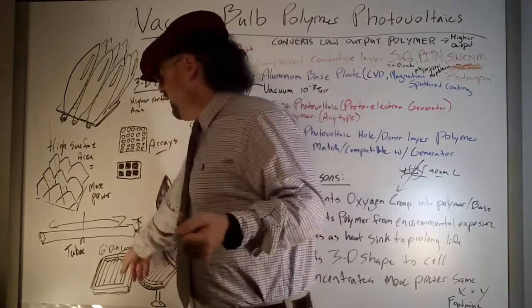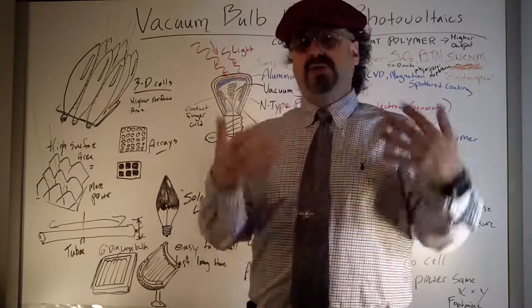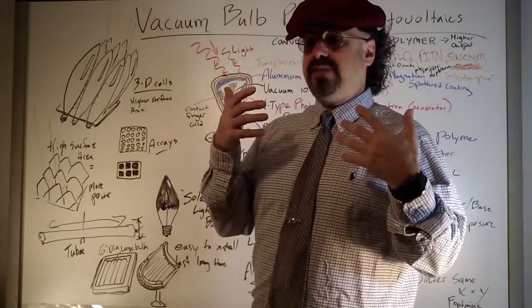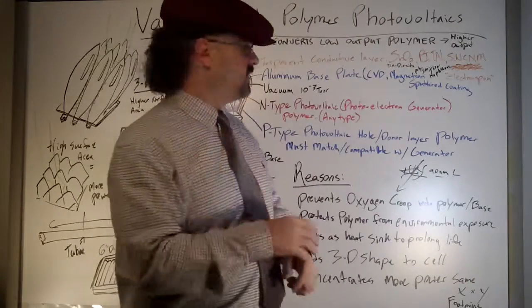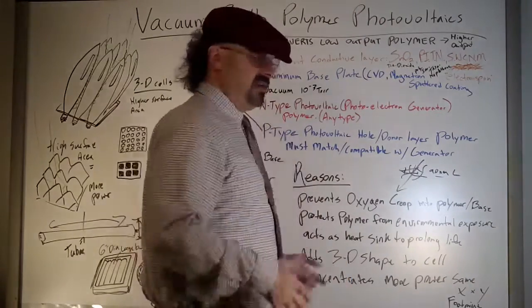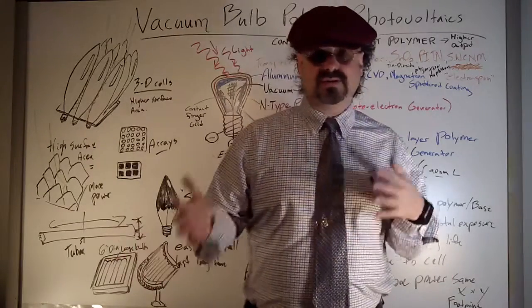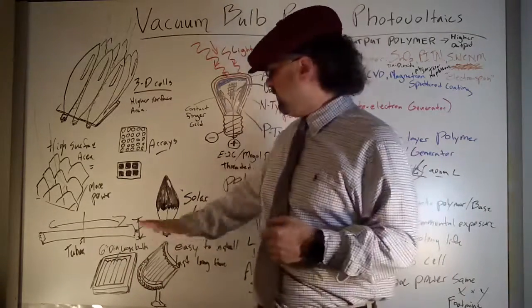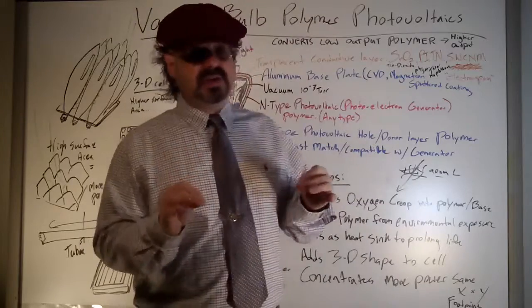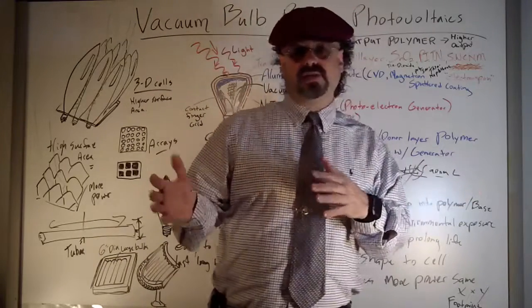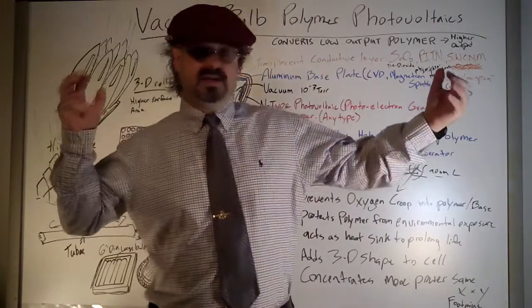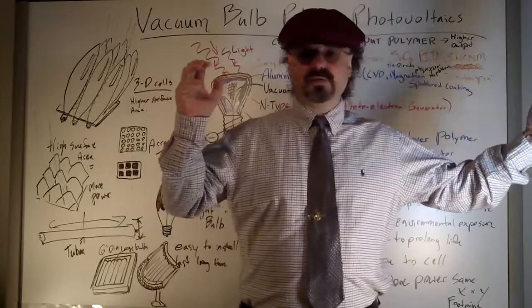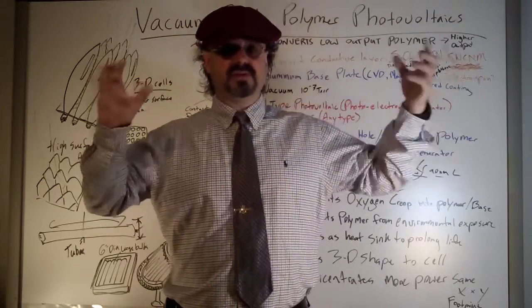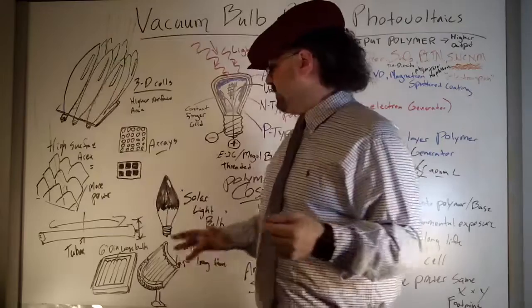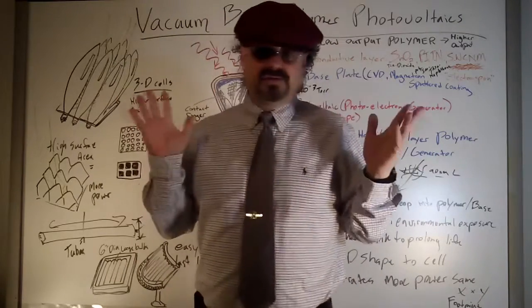Well, these are going to be vacuum evacuated glass tubes, but you're going to use the polymer to coat the inside of the tube, and that's going to be direct power, DC. You're going to have direct current coming from those coatings, which is going to be a step in the right direction, because they do have vacuum evacuated glass tubes that they're using for concentrator solar, where they heat up the oil, and that's pretty neat too. But I think I'd rather have just direct power.